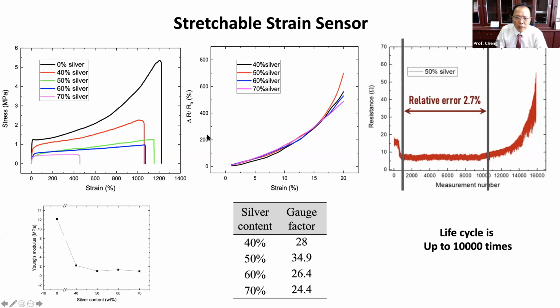In our electrical measurement, within 0 to 20% strain, within this deformation, 50% is the best performance. So later on, we use the 50% mixing ratio for our test. We also test the repeatability. You can see over 10,000 cycles it is very stable.